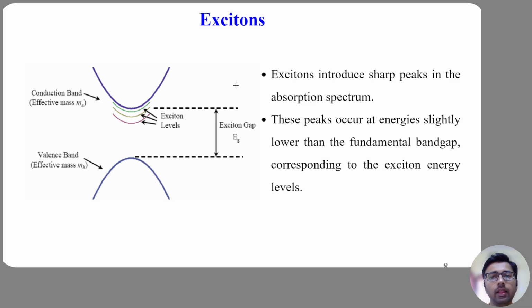By analyzing these peaks, we can calculate the exciton binding energy and the dielectric properties of the semiconductor material. Thus, excitons provide deep insight into material physics through spectroscopy.